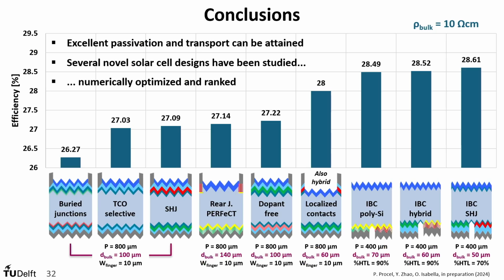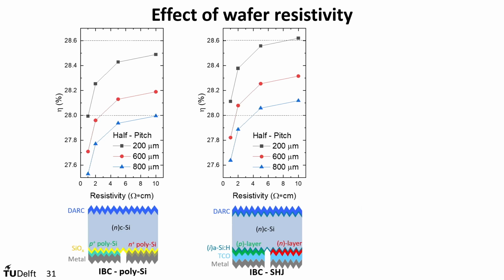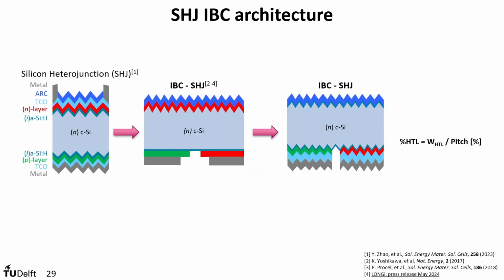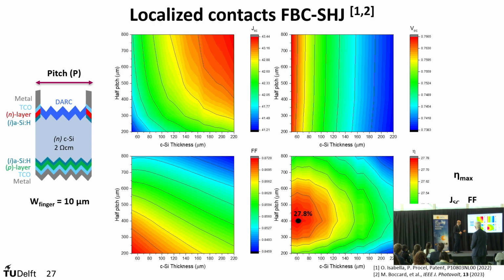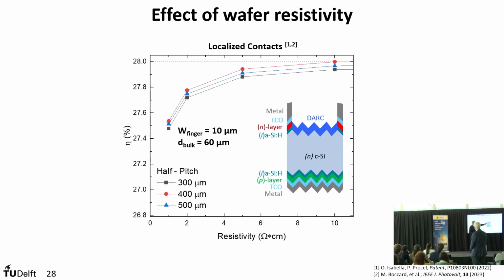Yes. The blue layer passivation? Yes. I didn't dive into many details, I think it was slide 28, but it's essentially very much straightforward. Essentially, we do everything here, then we do some back etching that has to be optimized, and there are a lot of tricks to work on that. This is essentially a silicon nitride that we deposit after the metallization. It is not sketched here because we are talking about 60, 70 nanometers on top of 5 microns of metallization, so you can pierce through it and do the measurement anyway.